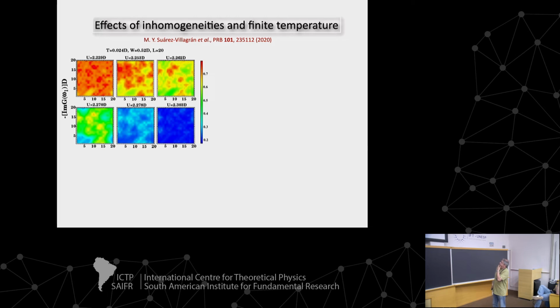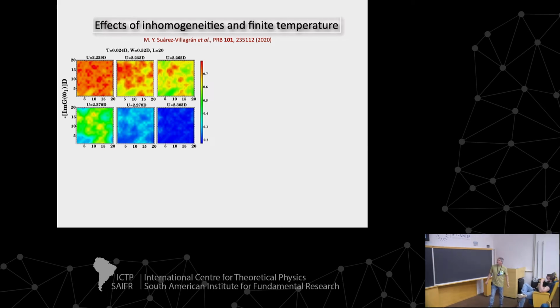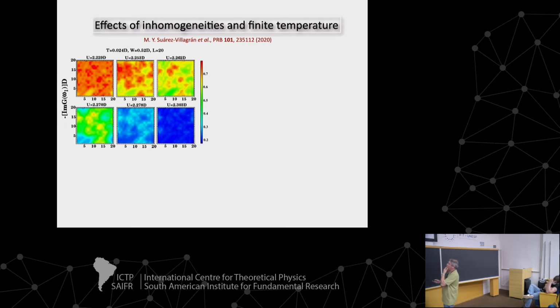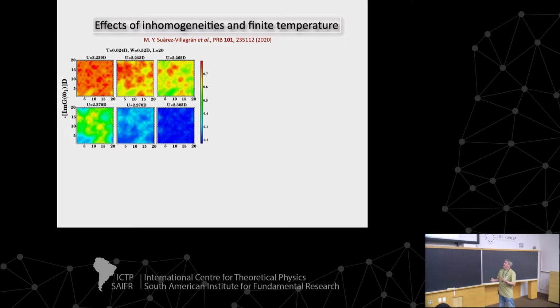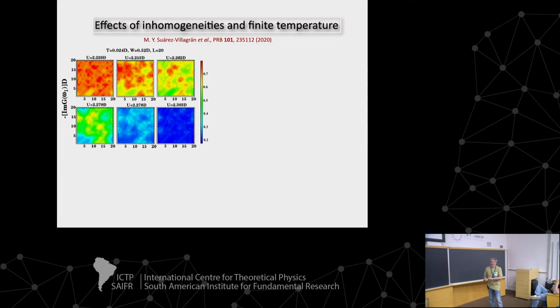Now, you can do that for the disordered Hubbard model. So this is the kind of results you have, full-scale calculations for 20 by 20 two-dimensional square lattices. This is a lot of work, as I said. And you can see, first of all, this is the imaginary part of the local Green's function, which is a measure of metallicity as opposed to insulating behavior. So when it's large, you have a metal. When it's small, you have an insulator.